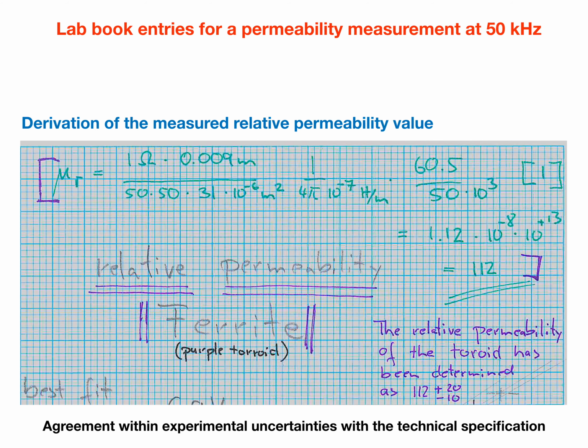Substitution of the appropriate parameters in the equation derived earlier gives a relative permeability of 112 with uncertainty margins of plus 20 and minus 10. This agrees with the technical specification for this material of 125 plus minus 20%.